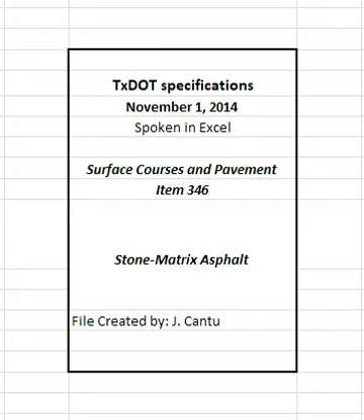2.6.3 Warm Mix Asphalt, WMA. Warm mix asphalt, WMA, is defined as HMA that is produced within a target temperature discharge range of 215 degrees Fahrenheit and 275 degrees Fahrenheit using approved WMA additives or processes from the department's MPL. WMA is allowed for use on all projects and is required when shown on the plans.